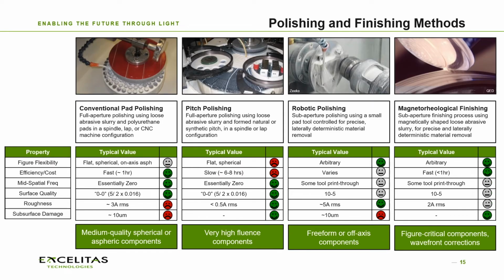Now, in terms of the polishing processes, this is going to depend on a number of factors, starting with the substrate material and the shape and form factor of the optical element. So for a small optic that has a very high demand for surface quality, roughness, scatter, surface finish, those kinds of things, conventional polishing, pad polishing, and pitch polishing are going to be outstanding processes for that. They're going to start to break down when the optics get a little bit larger.